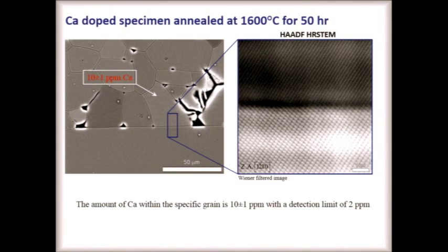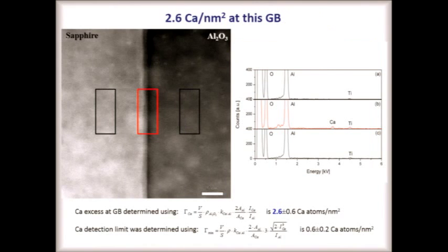which was 13 ppm. And we extracted a specimen, and this is just some simple high-angle annular dark field STEM, nothing really exciting, just to show that the grain boundary plane is more or less flat. And then we did spatial difference analysis in EDS. This is just a very good statistical method that has no spatial resolution limit to measure excess at a grain boundary or an interface. So we're rastering the beam in STEM mode in the grain, and in the grain, and then in a box, which is at the grain boundary.